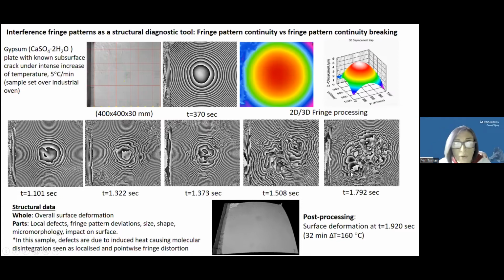I want to stress your attention to another detail that I didn't say, that there is a known crack. Look that the start of the discontinuity, of the disruption in the uniform distribution of intensity, starts from the point where we know that there is a crack, and from there it starts the, let's say, bigger separation of the discontinuities.